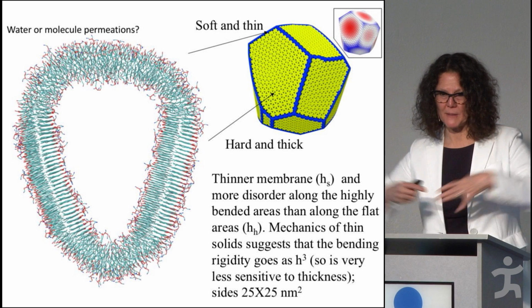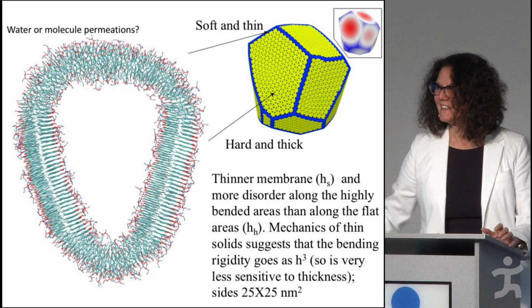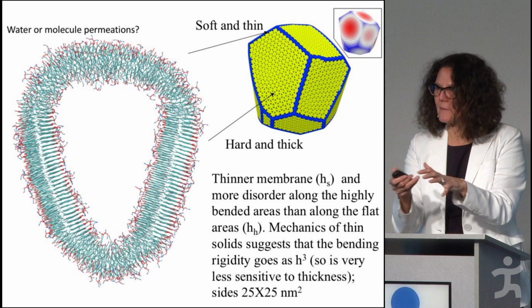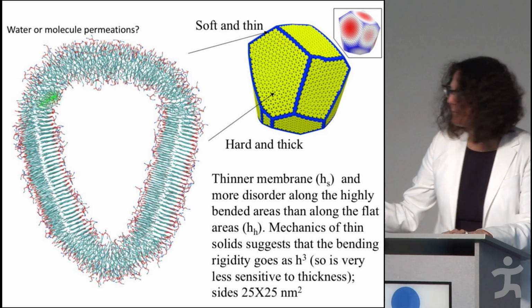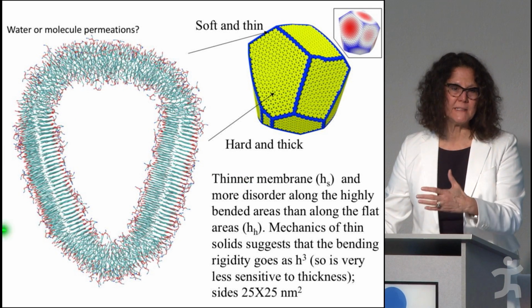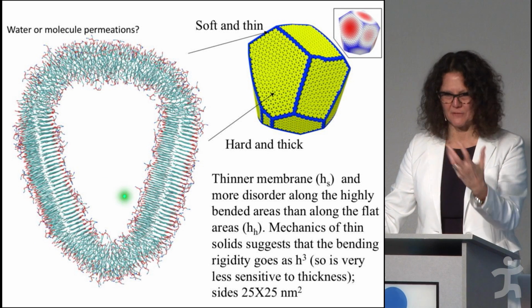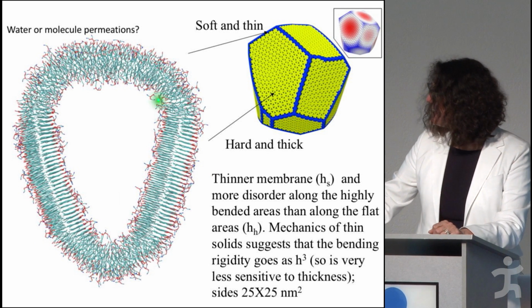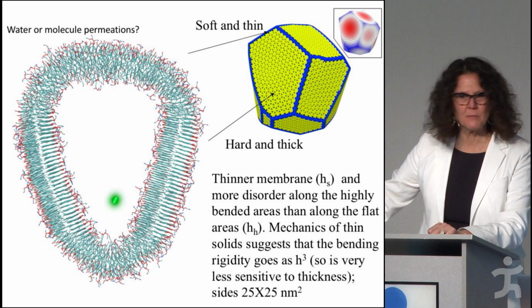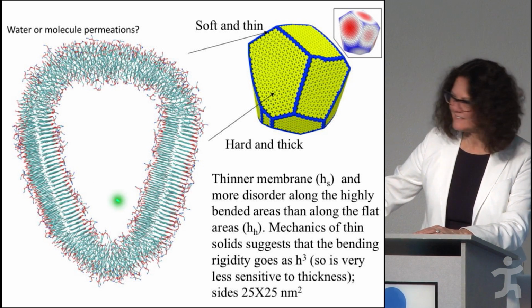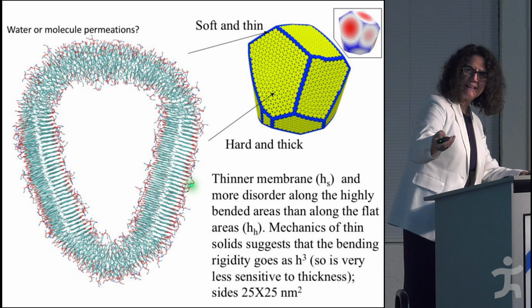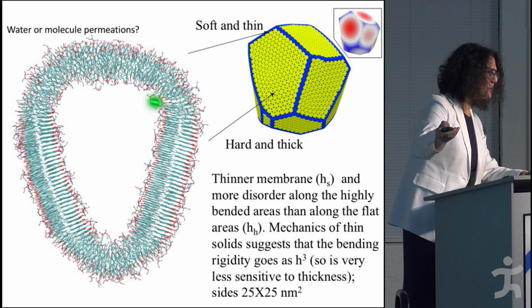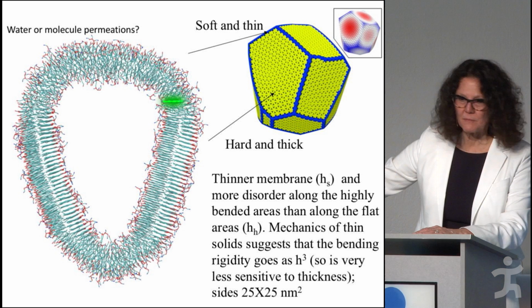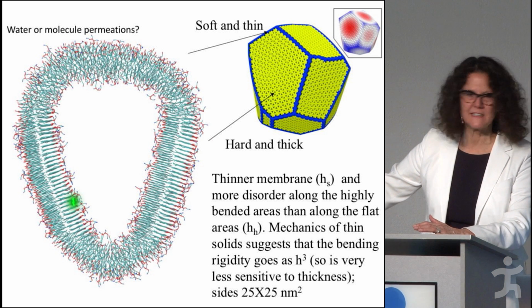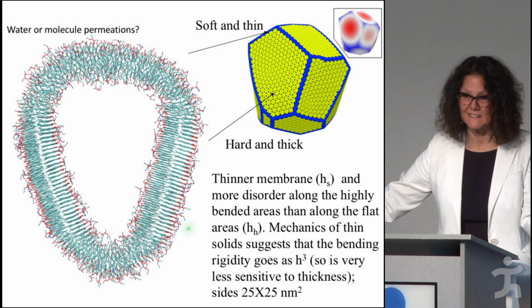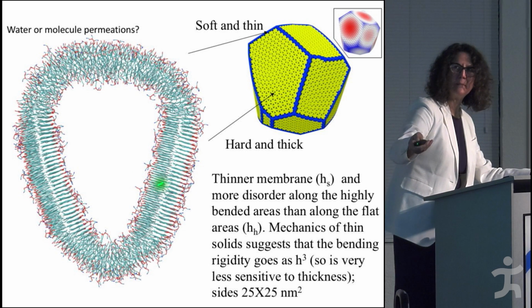Okay? They open up into the ribbons of these sheets. But when they have the hexagonal structure, they're able to close. And so when we go back to this model, which is called a Martini model, that is a coarse grain with the 4 waters, 1 bead, and so on, then you can see that it looks very much like the full atom when we have all the water and the structures, the bilayer. And here they look disordered, right? So here there is more permeation, the properties are different, and this is respected by what I showed you in the beginning, with the properties of the bilayers.